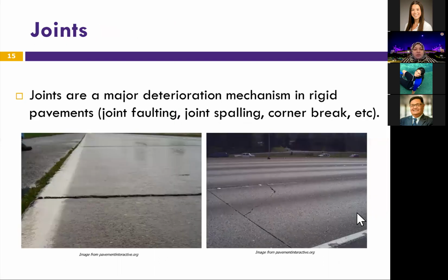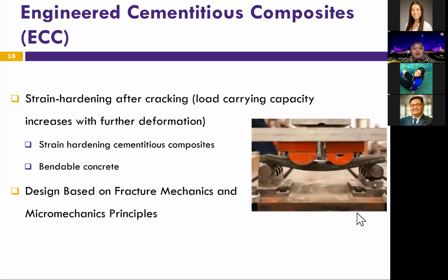In addition to all of this, concrete expands and contracts, and it has a high coefficient of expansion, which means we need joints in order to avoid cracks. But these joints are a major deterioration mechanism. So we see things like joint faulting, spalling, corner breaks, etc. One solution to a lot of these problems is the ECC.